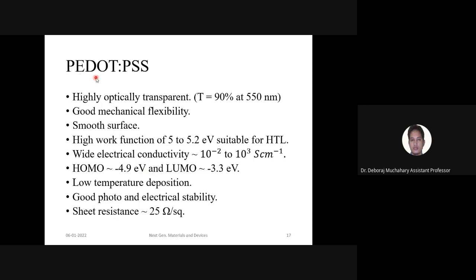Now another good one is PEDOT:PSS. So this is a polymer. This consists of two different compounds, PEDOT and PSS. Okay? So what is the advantage of this polymer is that it is a commercial TCO, transparent conducting oxide also. Here we have seen that PEDOT:PSS is highly optically transparent. The transparency is around 90%, T meaning transparency, at 550 nanometer. So at a wavelength of 550 nanometer, the transparency is around 90%.